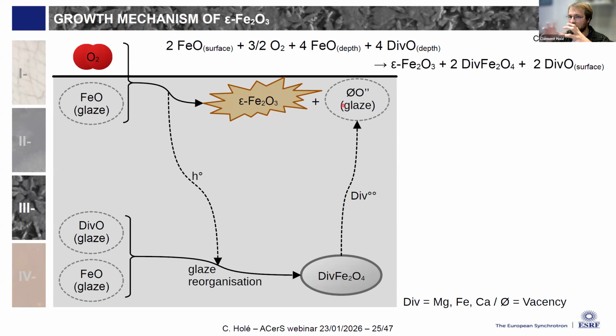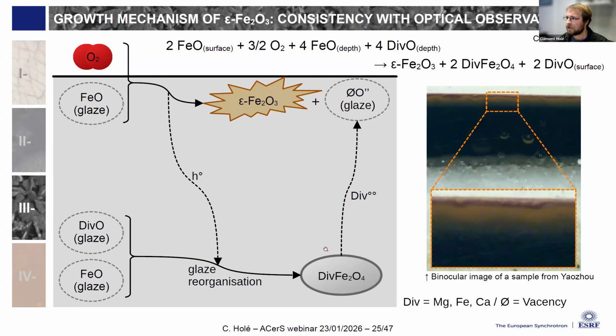And to stabilize itself, the glaze was actually pumping from deeper inside some divalent species, and these divalent species would actually fill these gaps, but then the inner glaze will be destabilized. And to restabilize itself, it reorganizes by crystallizing tiny spinel clusters. And this would perfectly explain why we have this iron epsilon oxide layer only at the surface, which has this characteristic brown. And below, we don't find any iron epsilon oxide, and we have this very typical black layer that can be associated to magnetite, though it's noteworthy that magnetite is very rarely found in this area. This black glass is very, very amorphous looking.